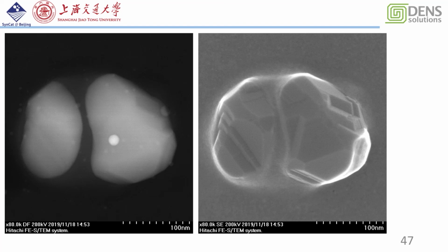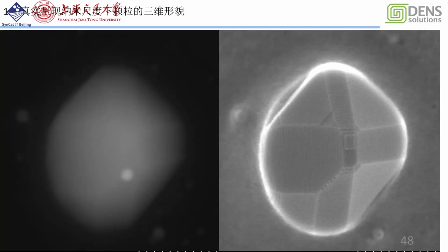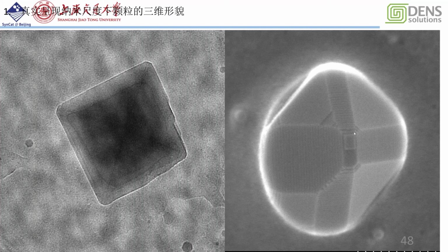They give very different information from the latter reference. But if we take the high resolution image of the secondary electron, we can see the iron particle. This is a magnetite particle. The surface is very complicated. And we can see with higher magnification, we can correlate this octahedral particle shape with the TEM image we got in this one. They prove that our observation in the in-situ TEM is right.